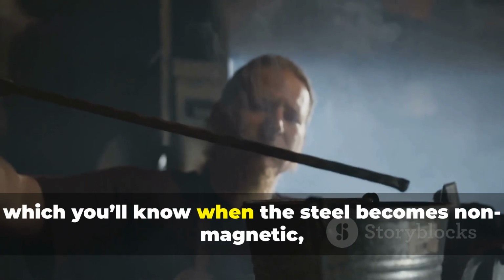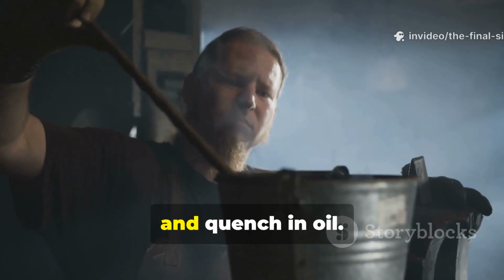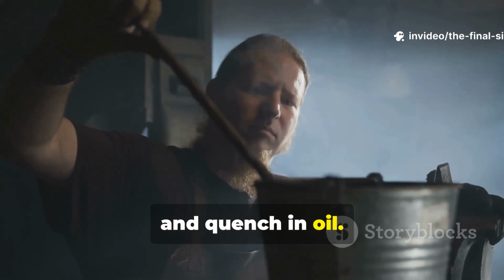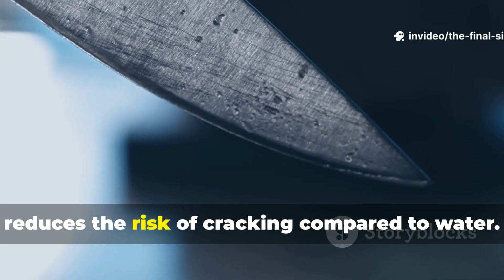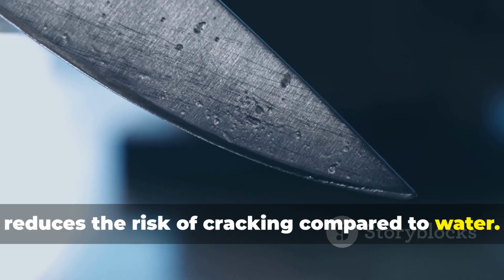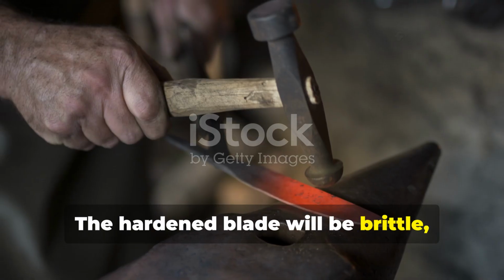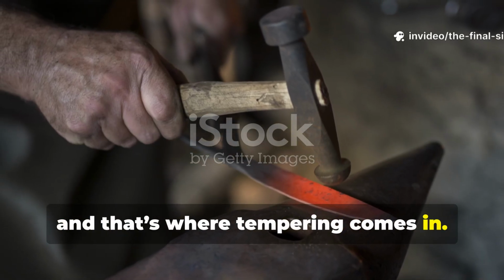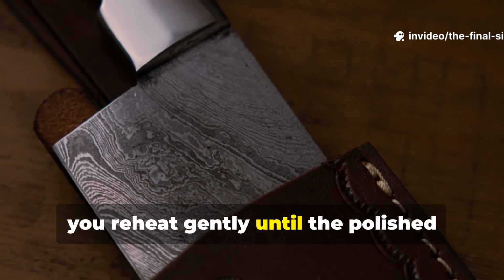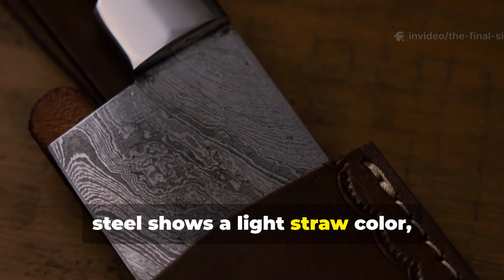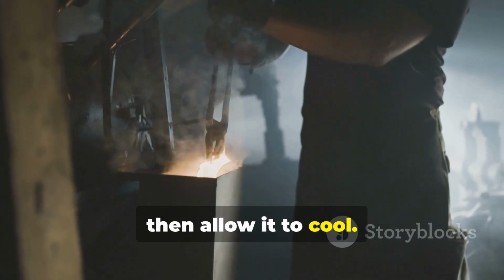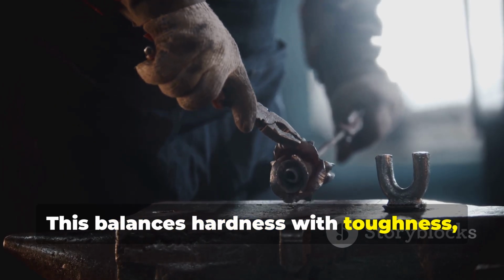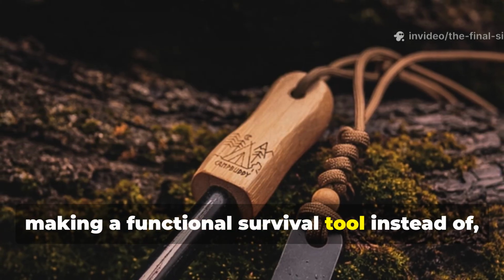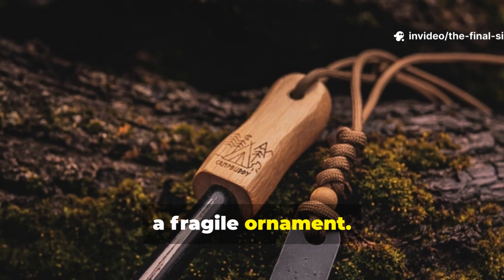Then reheat again to the critical temperature, which you'll know when the steel becomes non-magnetic, and quench in oil. Oil, by the way, reduces the risk of cracking compared to water. The hardened blade will be brittle, and that's where tempering comes in. So you reheat gently until the polished steel shows a light straw colour, then allow it to cool. This balances hardness with toughness, making a functional survival tool instead of a fragile ornament.